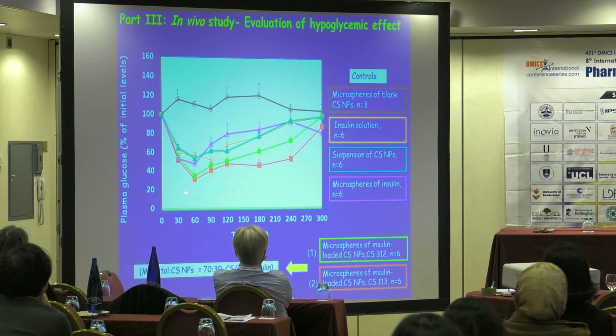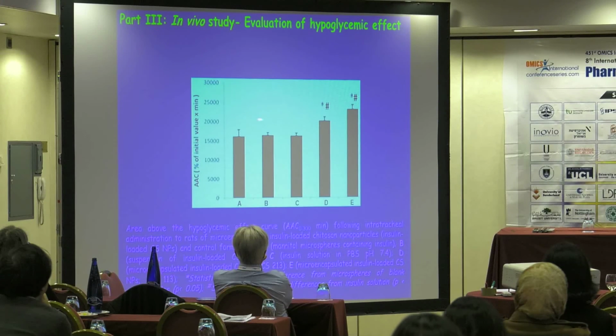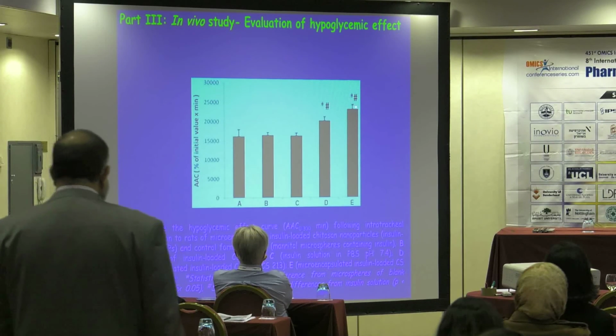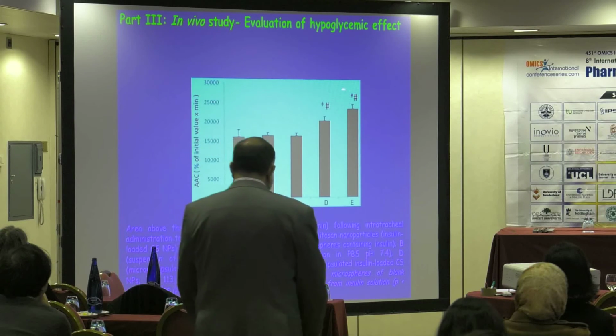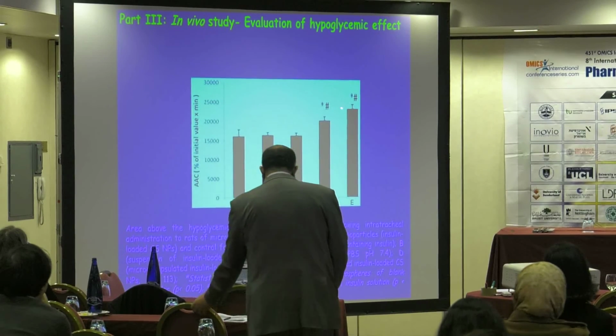If we look at the area under the curve, again we see the microencapsulated chitosan nanoparticles with the higher area under the curve being the best, for the ones which contain chitosan of molecular weight 113.